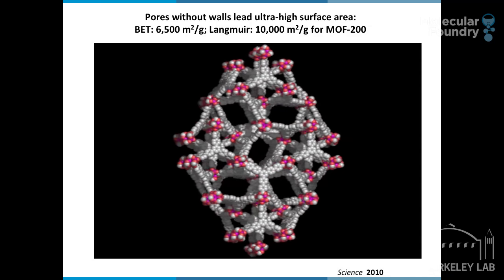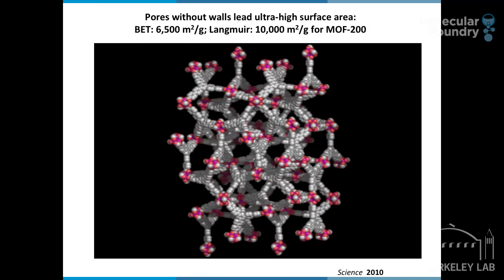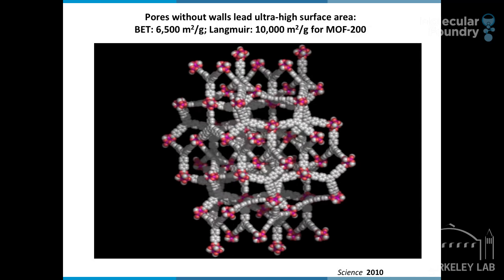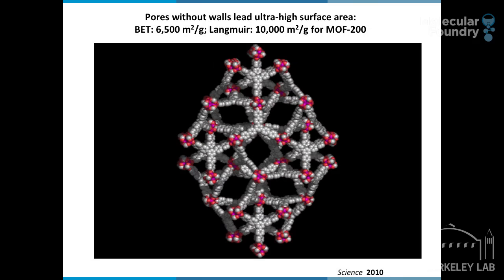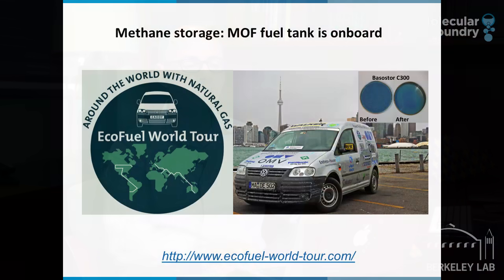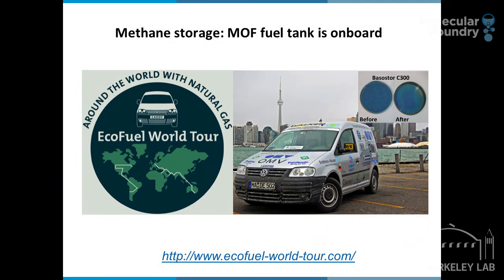It has a surface area of 10,000 meters square per gram. The new record is about 11,000 or so meters square per gram. And that's probably the upper limit for surface area of such materials based on 6-membered rings. So now we are all set, using this simple chemistry and our collaboration with BASF, to scale up the MOFs. We're set to put these MOFs in automobiles.